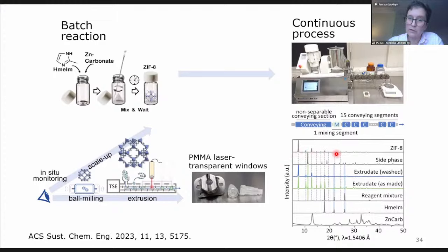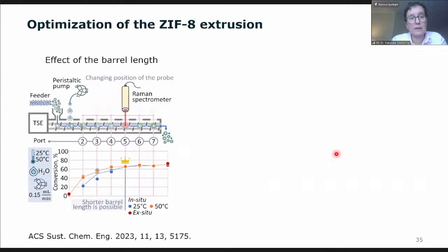So that was promising. And then we went on with our in situ investigation, and you see what we checked here. So first of all, we checked whether we need the whole barrel length, or if we can shorten our barrels a bit and have a conversion already. And see here different parameters we tested: temperature, changing in feeding rates, and also looking at the liquid we used. And the little crown guides you a bit where we try to find optimal conditions.